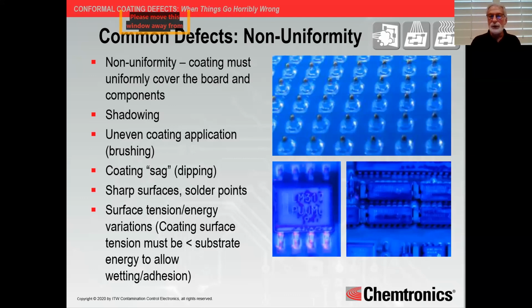You can have differences in the surface tension of the coating liquid as opposed to the substrate energy, and that can cause non-uniformity. In general, and this is in general, the liquid coating surface tension must be less than the substrate energy to allow it to flow for adequate wetting and adhesion and bonding energy to that substrate.